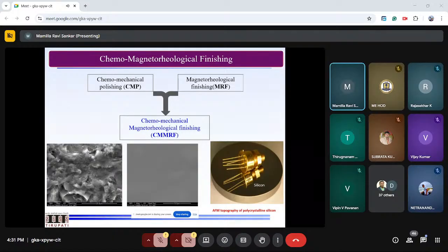so that you can make chemomechanical slurries. Since you have CIP particles, which are carbonyl iron particles, normally 99% pure iron particles, they will form a chain from the North Pole to the South Pole, where the diamond particles or any other abrasive particles are entrapped, and then you just have to finish it. Initially, the surface roughness is predominantly high. In those circumstances, you should always go for a high magnetic field intensity. That means 1 Tesla or above, and then you can do the finishing operation.